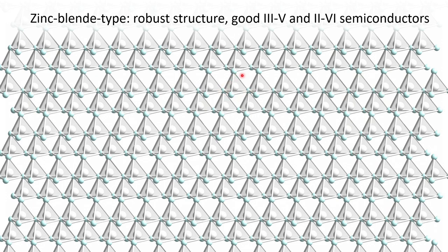The vertices of this tetrahedron that are shared between different selenium-centered tetrahedrons are cations. So now the stoichiometry between cations and selenium in this case would be 1-to-1. And these materials are very stable semiconductors, like III-V materials, for example, gallium arsenide, or II-VI materials like zinc sulfide, would belong to this structure type.